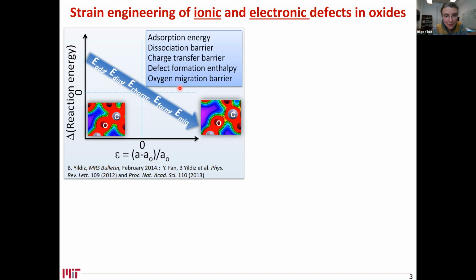And with this very high level sketch, what I'm trying to show is that when you apply compressive versus tensile strain, in most reactions that involve oxygen, these reactions become more favorable because we are reducing, for example, the migration energy barrier. We are making oxygen defects more favorable. We are making oxygen adsorption at the surface more favorable. And so it appears that as you change the energy landscape in the material by strain, the oxygen defects respond favorably to the elastic strain.